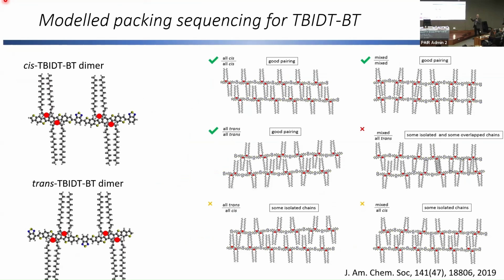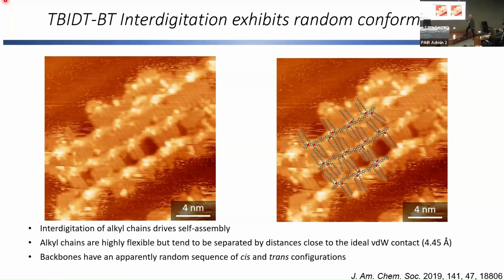I remember previously for IDTBT, there was no conformational arrangement where the side chains couldn't very nicely and very coherently interdigitate. But here you can see in the case of TBIDT, there's asymmetry in the spacing. And when you have that asymmetry in the spacing, you can't get rid of it by tilting, because it constrains the free volume. And when you have that asymmetry, as you can see here, it gives rise to holes.